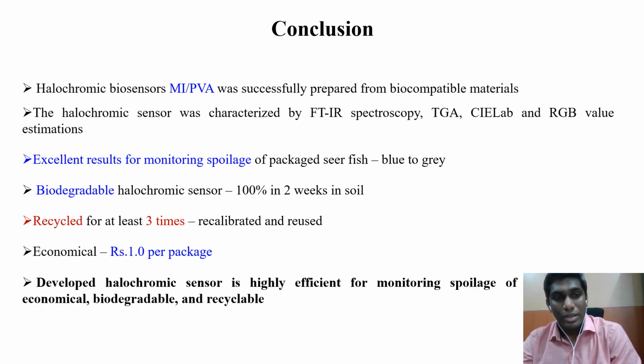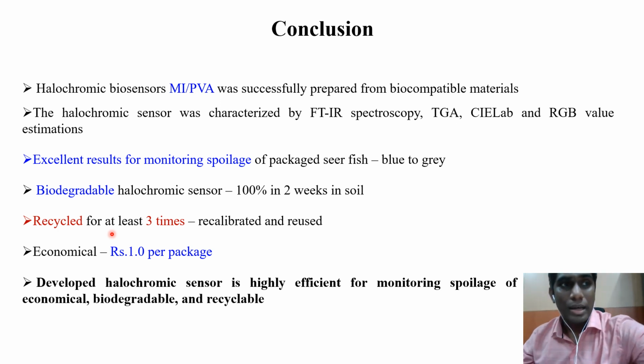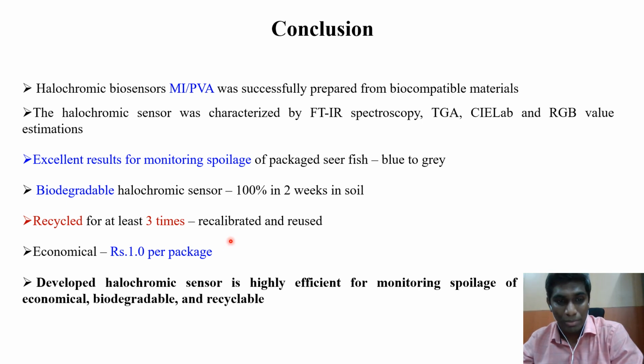In conclusion, we synthesized a halochromic biosensor, mixed indicator MIPVA, and we confirmed its successful preparation by means of FTIR spectroscopy, TGA, and the CIELAB values and RGB values. And the halochromic thin film sensor showed excellent result for monitoring spoilage of the packed seer fish. It shows color change from blue to gray, and it has a high biodegradability. It can be recycled at least for 3 times, and then it is highly economical. It costs only 1 rupee per package.